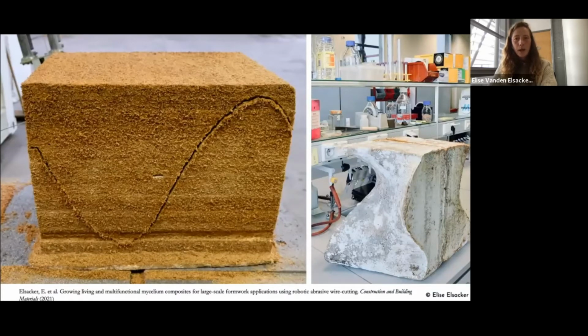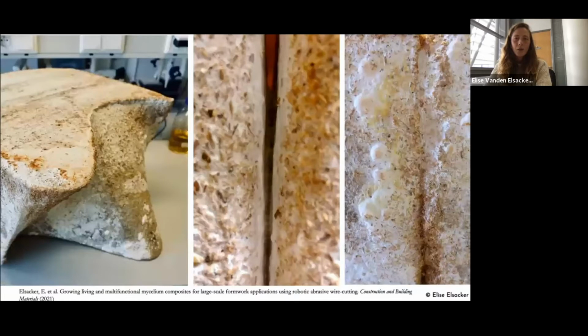So after the wire cutting process, the blocks were again sent back to Belgium, and the 2 pieces of the living block that you can see on the left image were reassembled. And then while the organism continued to grow, it produced a dense white grayish skin around all the exposed fibers, which you can see in the right image. And during that fourth incubation phase, the humidity was increased a lot until 90%, which allowed the hyphae to also bridge the gap of about 5 millimeters between those 2 elements. And so the two pieces were reconnected.